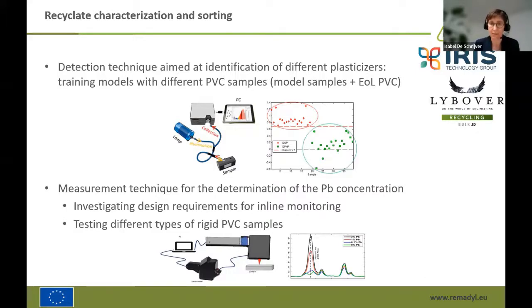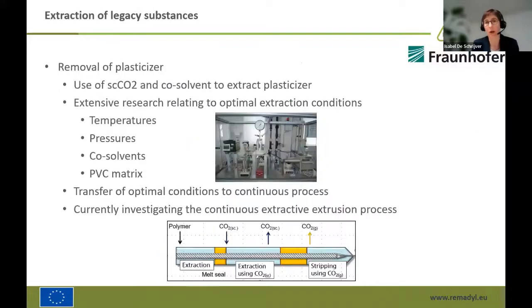Once we have identified the material, the next step is to have a look at how we can remove those legacy additives. Because PVC is still a very interesting material. It's a very useful material to recycle, but we want to get rid of those legacy additives. And for the removal of the plasticizer, we do make use of supercritical CO2, which is being considered as a kind of green solvent, together with some anti-solvents or co-solvents to extract the plasticizer.